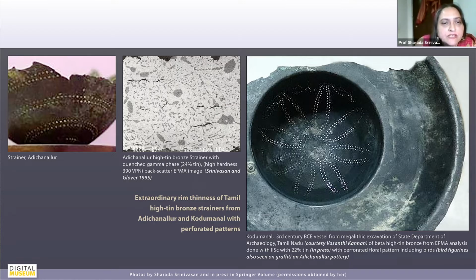And you're looking here at a backscatter image of a microstructure, using electron probe microanalysis, of the strainer fragment from Adichanallur. And in fact, this is of a slightly higher phase as well. It's called the quenched gamma phase, because as the alloy cools down from the beta phase temperature, there is the formation of the gamma phase, which happens before it goes to delta. So this is the quenched gamma phase, which is even harder, 390 VPN or so. And it seems to have actually been quite a resilient alloy, and probably because of the hardness, they could make these perforations as well.